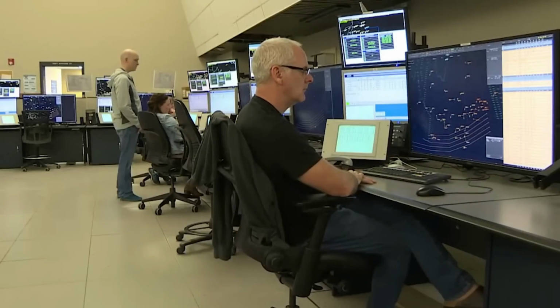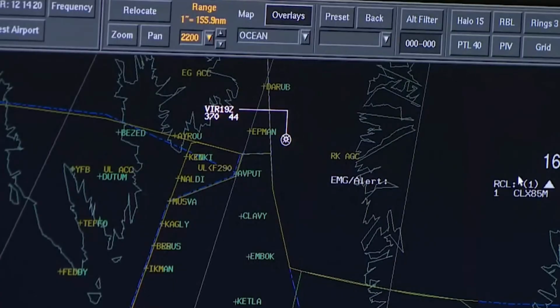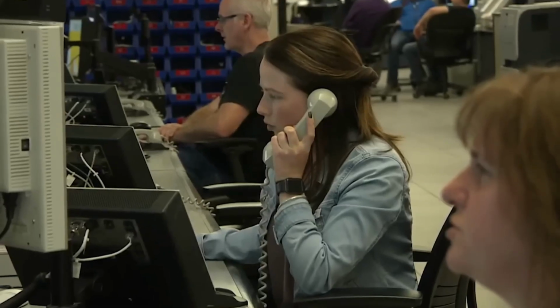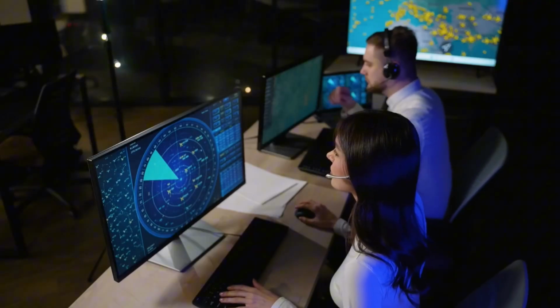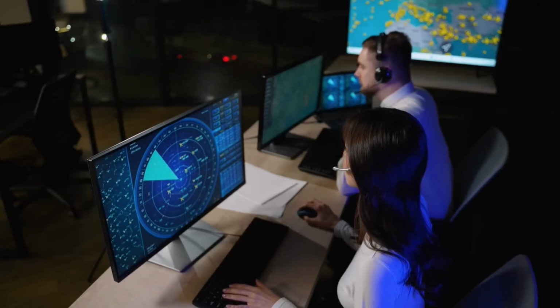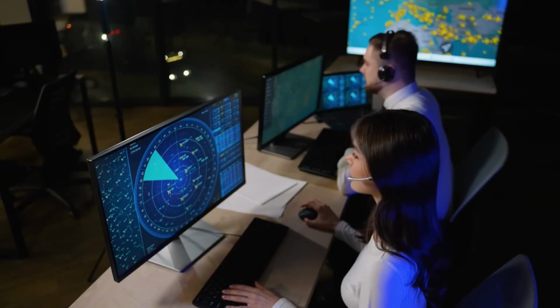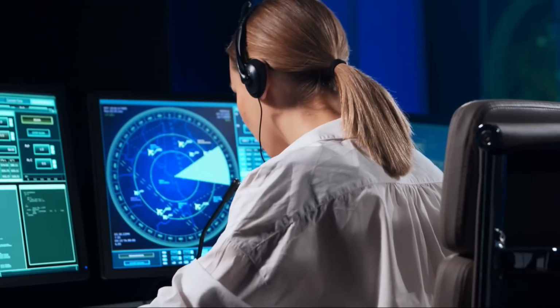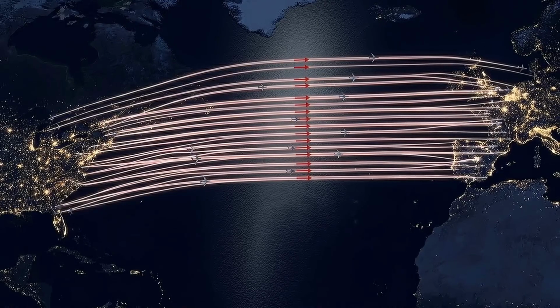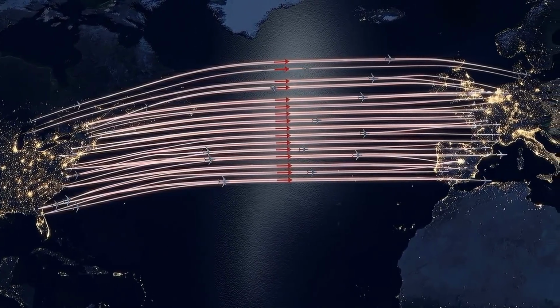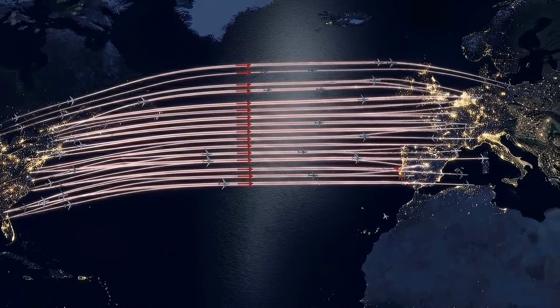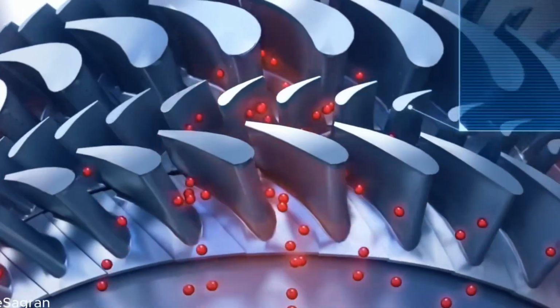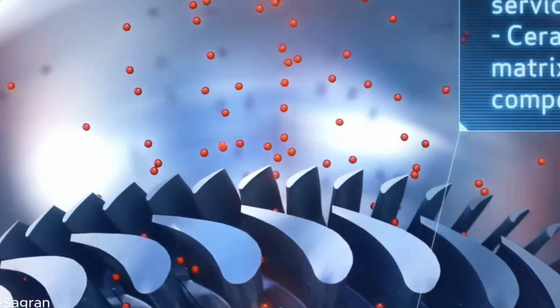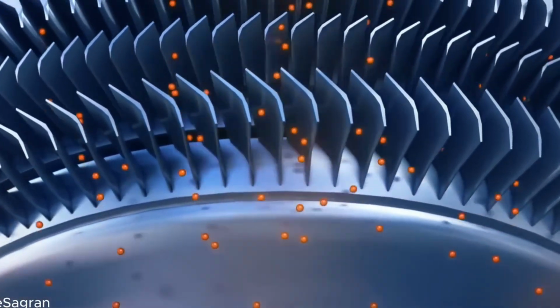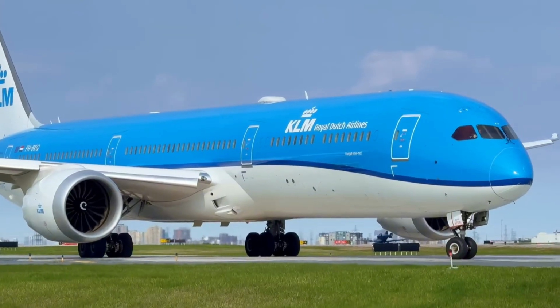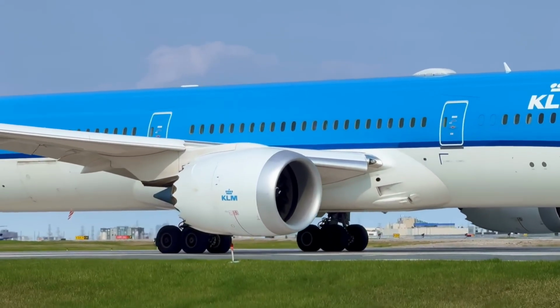But the chemical composition is only part of the story. What happens at the microscopic level is where things get genuinely fascinating. Inside these superalloys exist two structures known as the gamma phase and the gamma prime phase. The gamma phase allows a degree of ductility. The gamma prime phase acts as a barrier that blocks the movement of crystalline defects called dislocations. And that matters enormously, because dislocations are one of the primary causes of deformation in metals. The harder they are to move, the stronger the material becomes. That's why these alloys maintain their structural integrity even beyond 1000 degrees Celsius. But there was still another problem to solve.